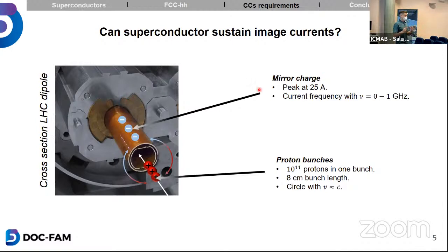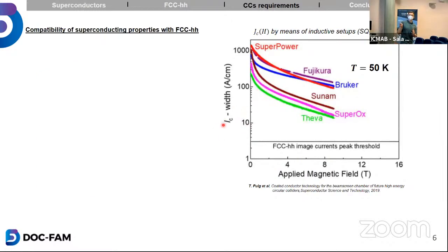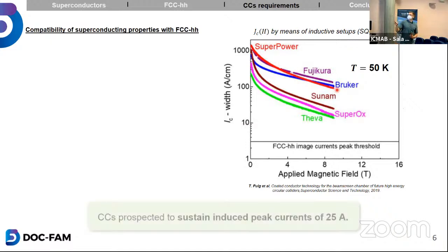A superconductor cannot sustain an infinite amount of large currents. And that's why we measured the actual critical current, so the current at which the superconductor transits from the superconducting into the normal state. We measured it as a function of magnetic field for several coated conductors. There are 2 things I want to point out. First, it seems like at 16 Tesla, so this is the operational magnetic field in the FCC, or the maximum magnetic field, the coated conductors will most likely be above the 25 amps of the induced peak currents.